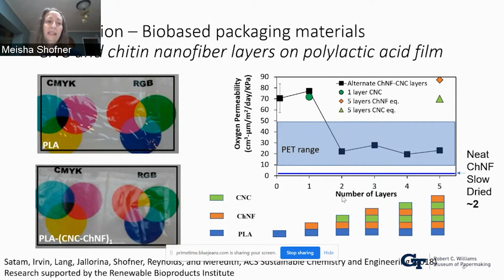So what we have been looking at is how to modify the barrier properties of polylactic acid by including more natural polymers. So basically coating these materials with cellulose nanocrystals, taking the polylactic acid film, putting a coating of cellulose nanocrystals, and then also a coating of chitin nanofibers, which is a different kind of bio-based nanofiber derived, at least in our work, from crab shell waste, but it also can come from different kinds of mushrooms.